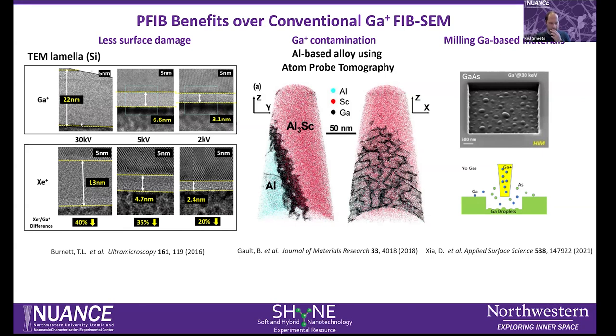Silicon's atomic structure can get disrupted by impingement of gallium ions. The yellow lines here indicate an amorphous silicon layer in this sample, and you can see at 30 kV the xenon gives about a 40% reduction in that surface damage layer. Even at lower accelerating voltage, the difference is smaller, but you can still see a benefit as to why you would prepare a sample here with xenon.